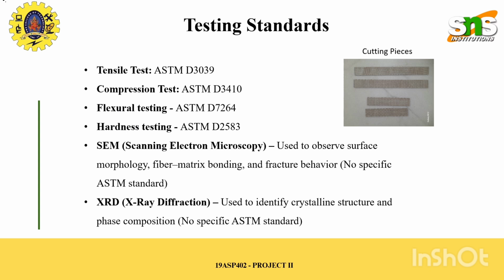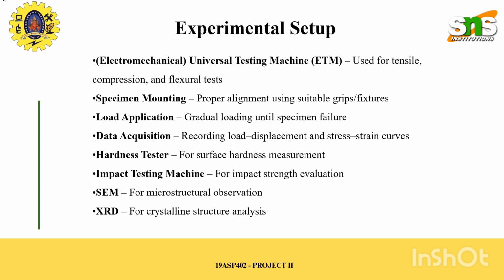To ensure reliability and consistency, standard testing procedures are followed. Tensile testing is conducted as per ASTM D3039, compression testing follows ASTM D3410, and flexural testing is based on ASTM D7264. Hardness is measured using ASTM D2583. In addition, SEM is used to observe surface morphology and bonding characteristics, while XRD helps in identifying the crystalline structure and phase composition of the material.